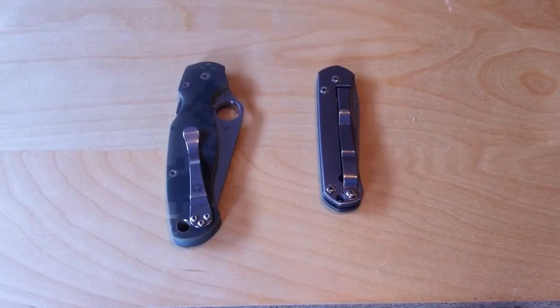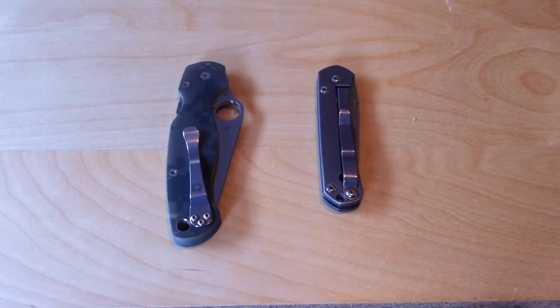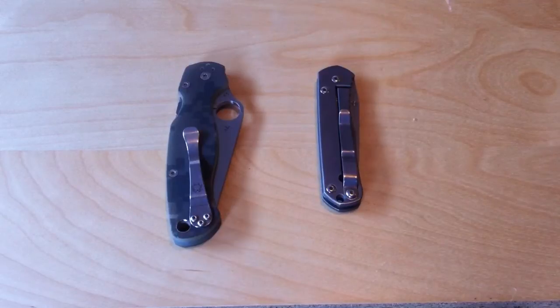An example I believe for S30V here, so both S30V knives, and I believe S30V the bottom of the recommended is like 58 and the upper end is 61. So they recommend the knife being in that bracket of hardness.